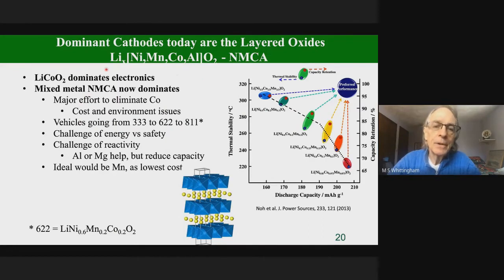Let me show you what some of the challenges are working with these layered oxides. This is a typical formula of a layered oxide: nickel, manganese, cobalt, and aluminum. So we call them NMCAs. As I mentioned, cobalt dominates electronics today. For most other applications, it's the mixed metal ones. There's a huge effort ongoing now to reduce or try to eliminate all the cobalt. This would cut the cost significantly.